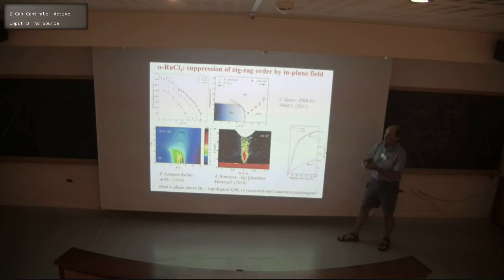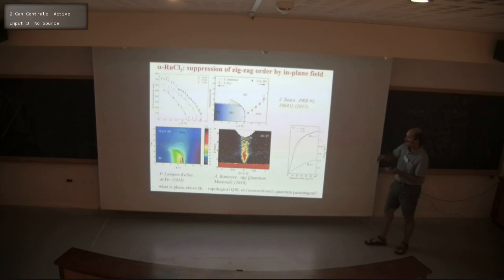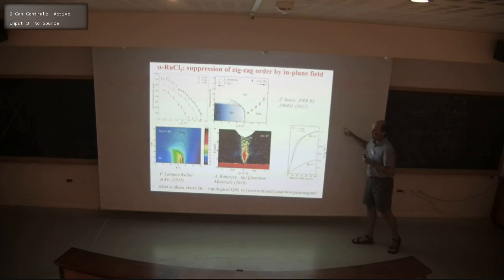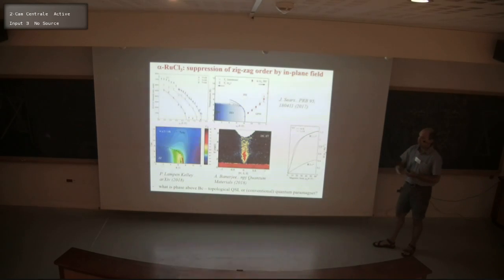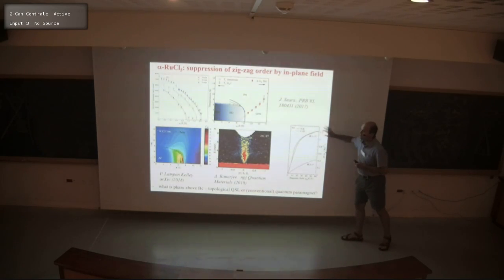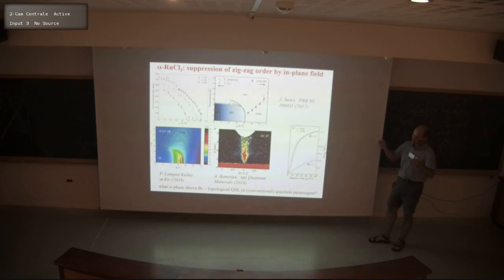Here, the excitations are gapped spin waves, and they're protected from decay into something else because of the gap. So what's happening is the ground state becomes dressed by zero-point quantum fluctuations, but ultimately, those can be squeezed away by increasing the field. So this is continuously connected to the ferromagnetic phase. So we still have sharp magnon excitations, but they're dressed by fluctuations. But there's no fractionalization. So this region up here, close to saturation, is understood as a ferromagnet dressed by quantum fluctuations, but essentially qualitatively the same.